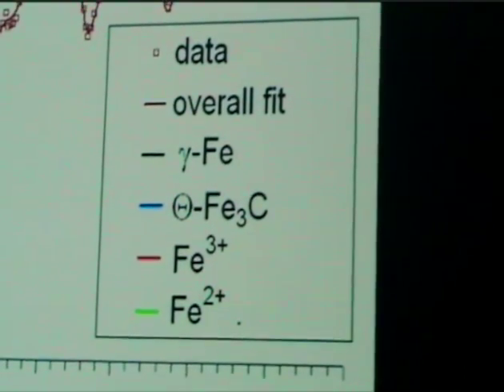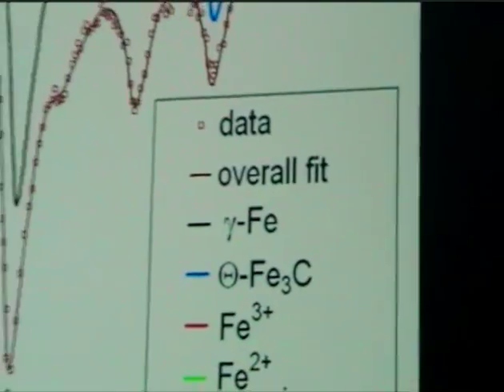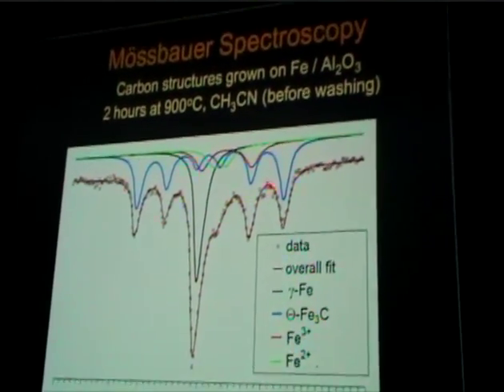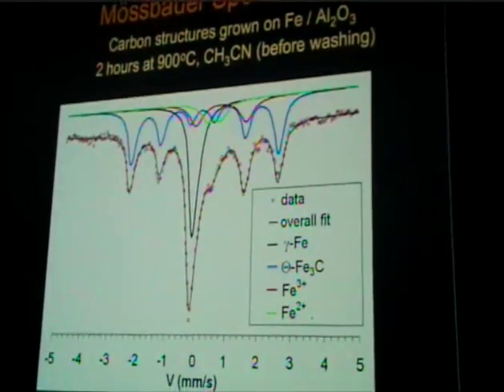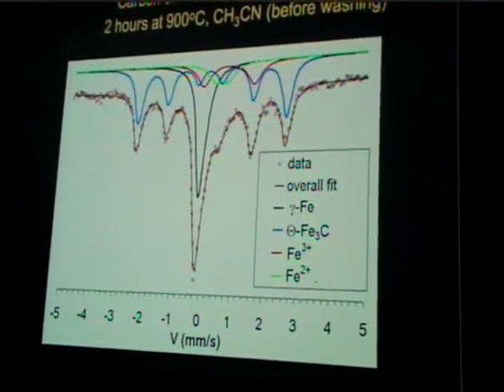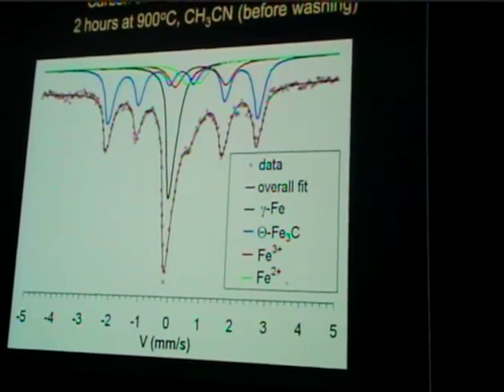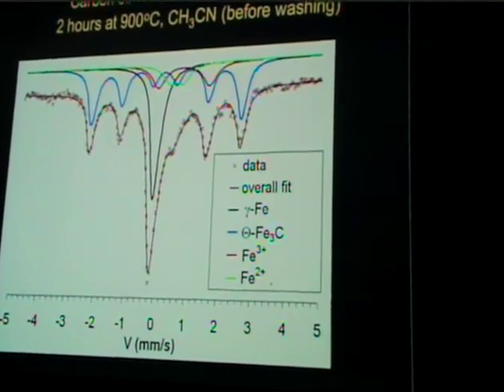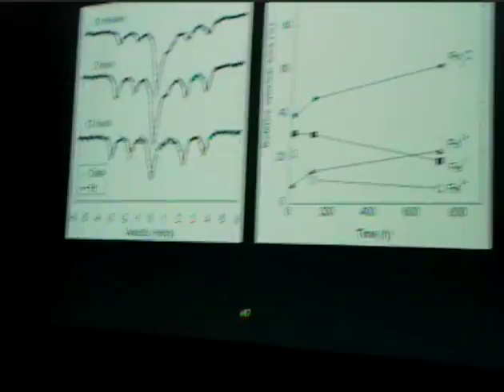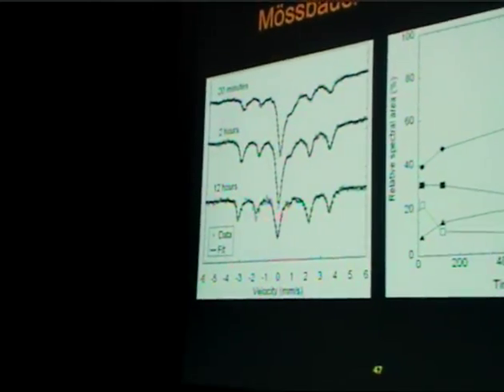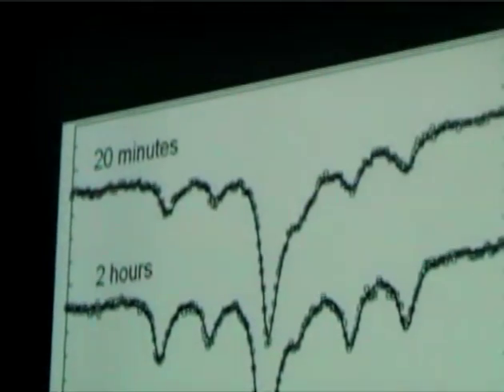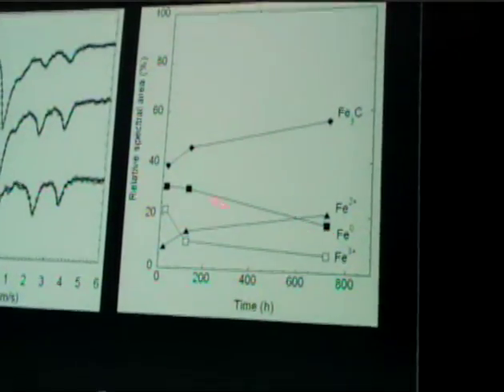And if we look at these carbon structures, these are before washing, and it is possible to really differentiate the nature of the iron. Most of what we see is cementite type carbon iron carbide, but we also see metallic iron and very small amounts of partially oxidized iron. Now, if we look at how the spectrum is changing with the time of the pyrolysis, as you can see, the carbide signal is growing and the paramagnetic iron, metallic iron, is coming down.